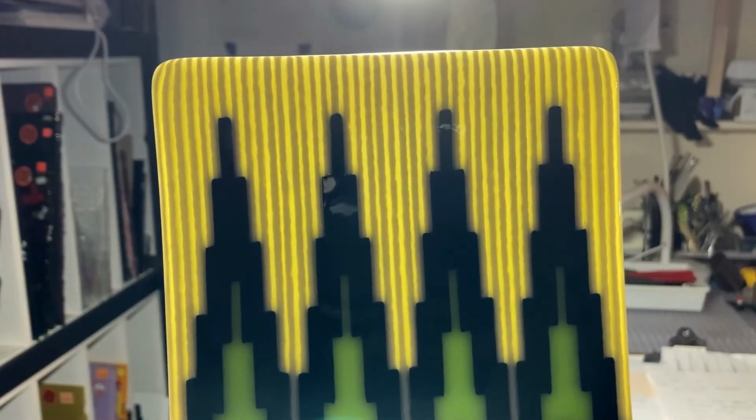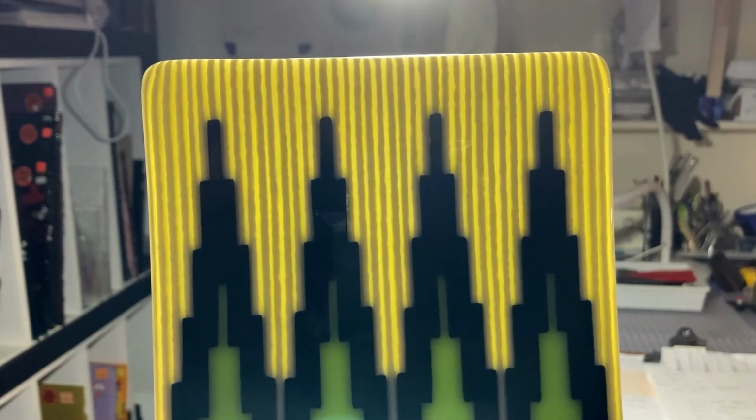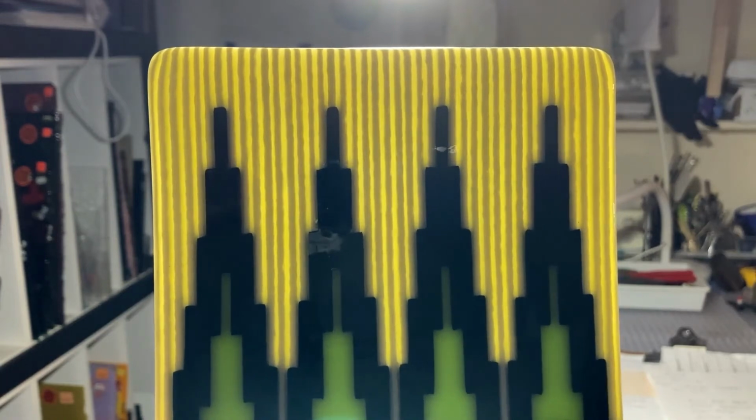Well, there's one thing you can say about glass fusing, and that is it's full of surprises, and they're not always good surprises, but this one was. Now, I did notice that when you hold up normal unfired French vanilla, it's translucent, so if you hold it up to the light, you can get that nice glow through it. If you hold this up, you can see where the joins are, it's retained that translucence, but the actual body of the strips has turned pretty much opaque white, or very close to white anyway. So that's very interesting. I'd like to know more about what reaction is going on there. Not quite sure where I can find that out, maybe through Bullseye themselves. Or if somebody at Bullseye is watching this, please let me know.